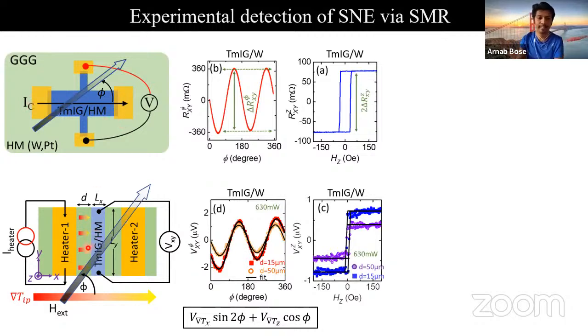Our experimental detection mechanism is the following. We run both electric current and thermal gradient, and measure the Hall voltage and compare them. By the way, we are measuring in TmIG heavy metal bilayers. Our heavy metals are either tungsten or platinum. We chose tungsten or platinum because they are strong spin Hall sources. We rotate the magnetic field in the plane and we sweep the magnetic field out of the plane. When we rotate the magnetic field in the plane, we get a sinusoidal sin 2φ angular dependence. That's why I call it a PHE-like signal. And when we scan the magnetic field out of the plane, we get a step in the resistance, so I call it an AHE-like signal.